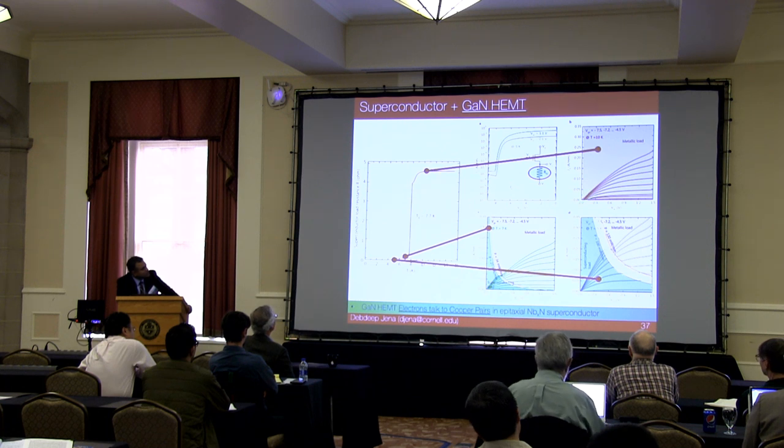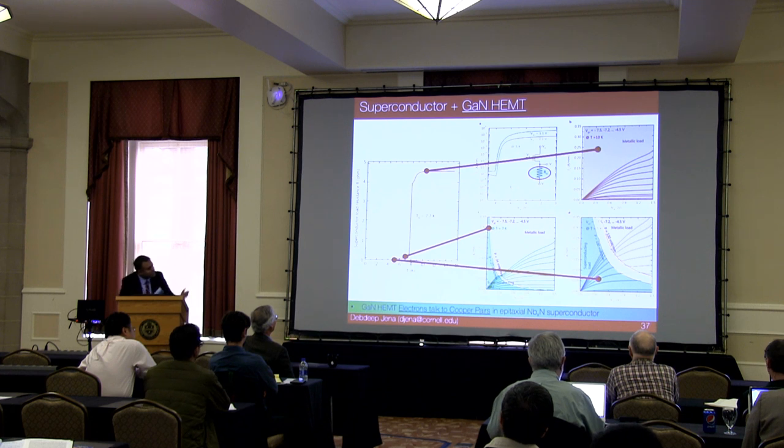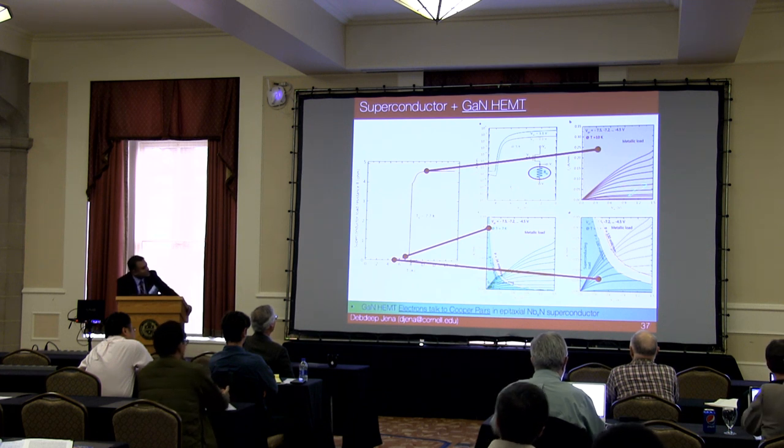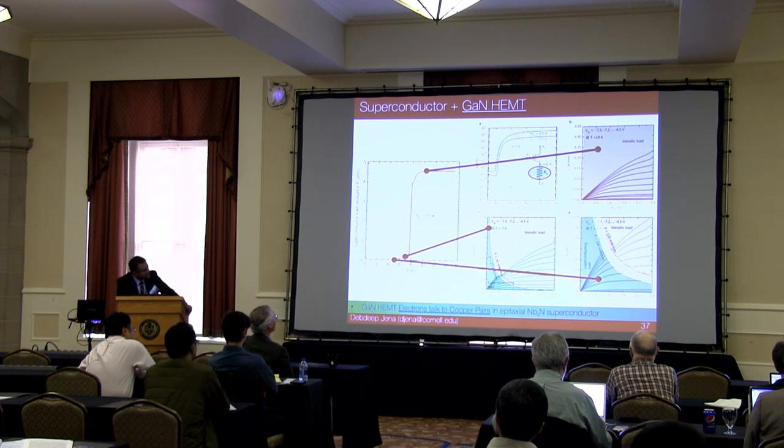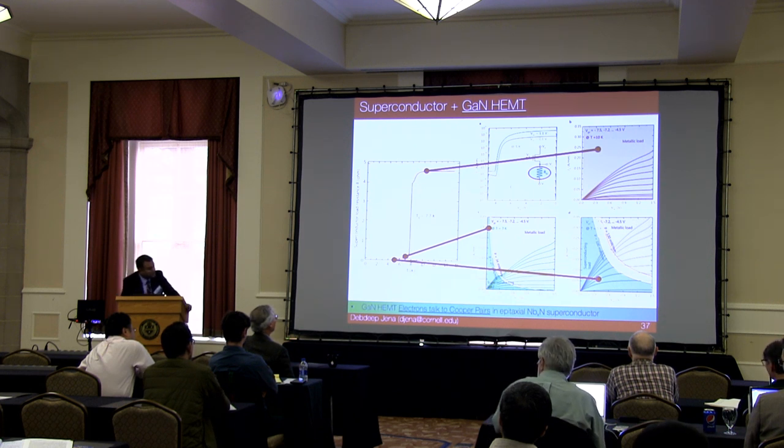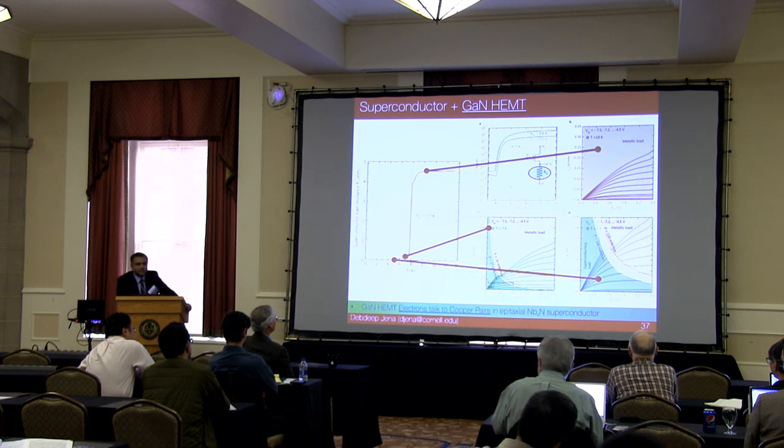But you have to convert a microwave photon to a visible photon, and with very high fidelity, because it's one photon. You can't lose it, right? And this is, I think, a very interesting breakthrough, not from my group, but a collaborator, Hong Tang at Yale. What they used is aluminum nitride or gallium nitride-based materials, because these materials are semiconducting, but they're also very piezoelectric.